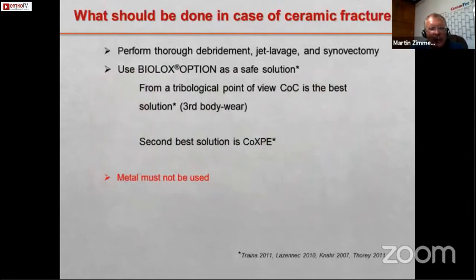Why, and what should be done in case of a fracture of a ceramic where you make an exchange? First of all, you have to perform a thorough debridement, jet lavage, and synovectomy, because actually it is impossible to get rid of all these ceramic particles. Most of them you can see, they are large enough. If you do the synovectomy, it will take a lot away, but there are a lot of microscopic particles which will still remain inside the articulation.